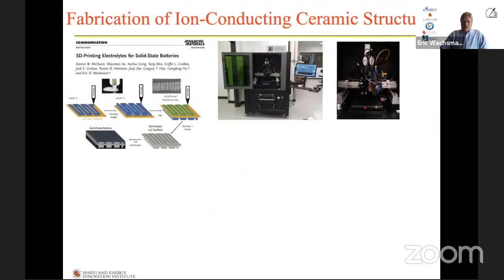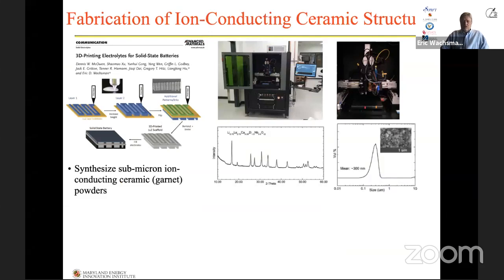So the basic process, like I said, is we scan a printing capillary around using the 3D printer as shown here. You can read more about it in this Advanced Materials paper we published. The first step is to synthesize your ion conducting ceramic, again, in this case, garnet, and there's the composition of one of them. They have to be sort of sub-micron size, and so you can see a volume percent versus size plot there, and an SEM image of some of the powders.